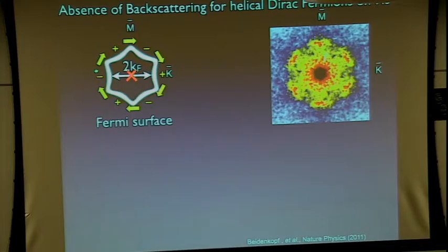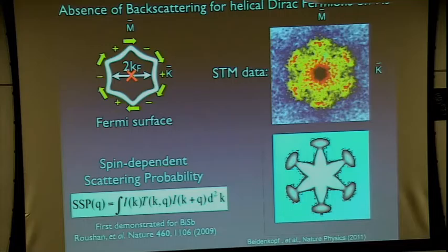So what we started with was just the one thing going around in a circle, electrons and momentum and spin being locked together. And now here you have also an out-of-plane component of the spin as you go around this Fermi surface. Okay, and this turns out to be key because that also forbids scattering processes of these surface electrons.